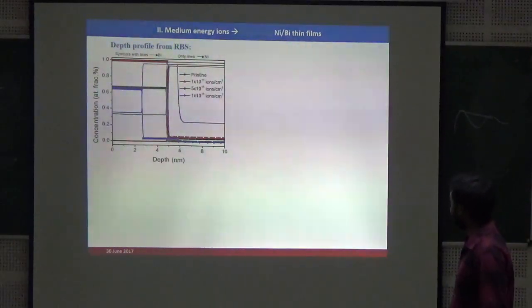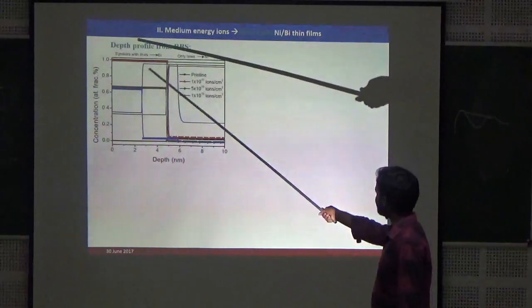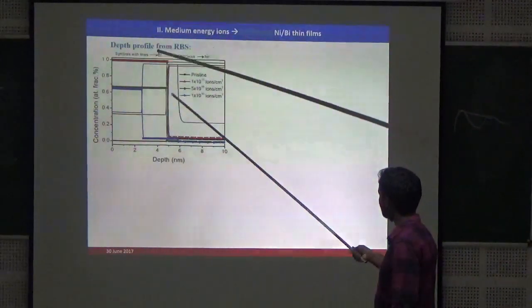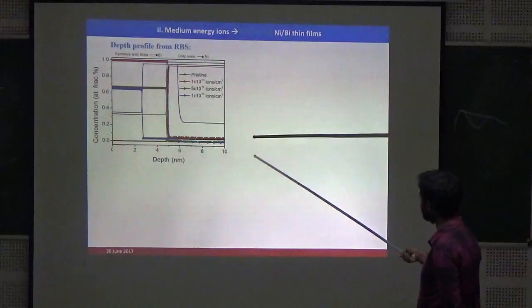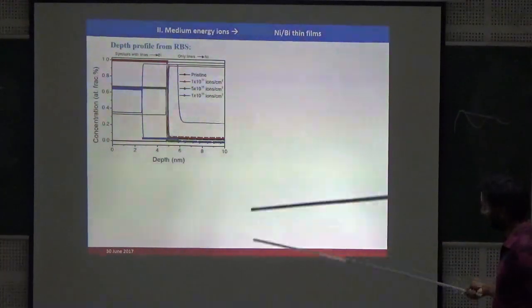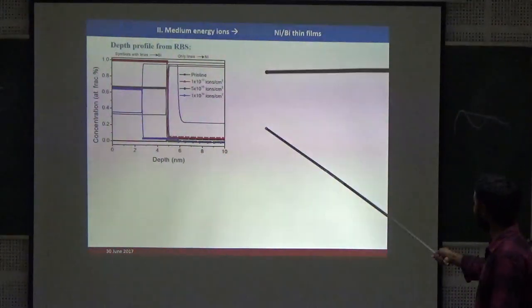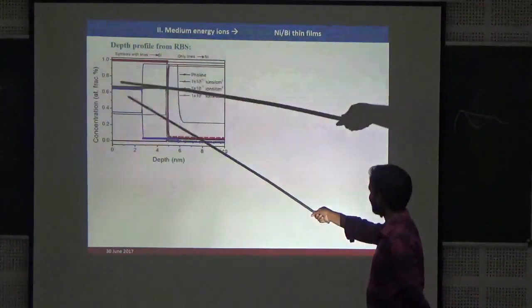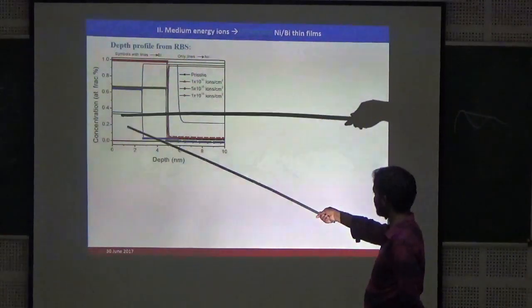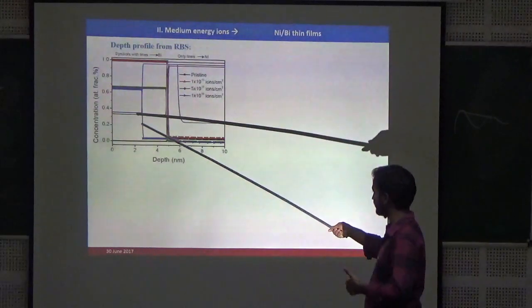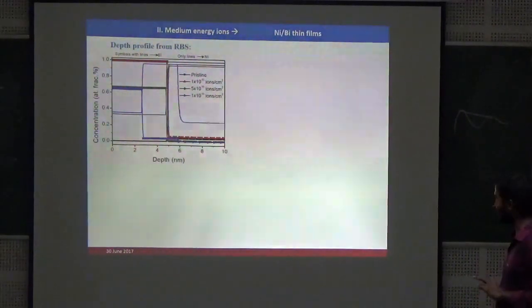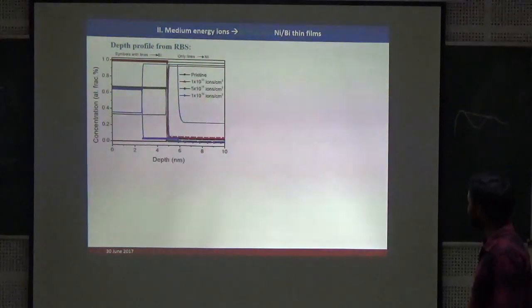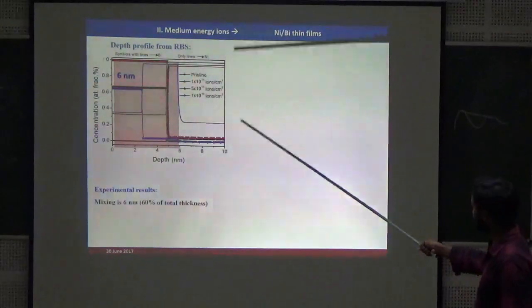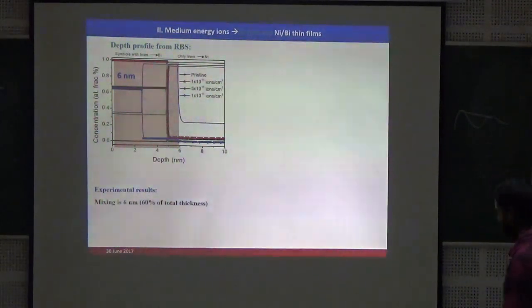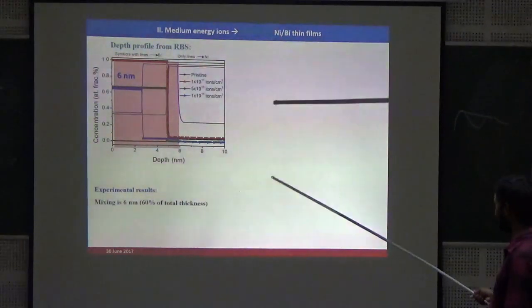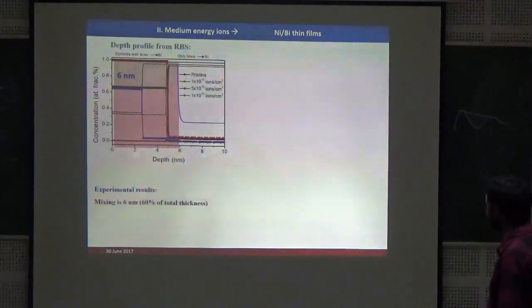So the depth profile is almost 1 in case of surface, and it is almost 0 in the nickel layer. But after increasing the ion fluence to a fluence of 5 into 10 power 15, you can see it is naturally coming down. It is almost 0.63, the ratio of bismuth and nickel is 0.63 and 0.37. So that means it is responding very rapidly to the ion beam. That means this is the enhancement region after irradiation. So 6 nanometers is the enhancement in the mixing, which is 60% of total thickness.